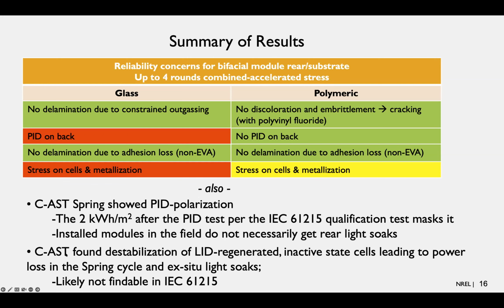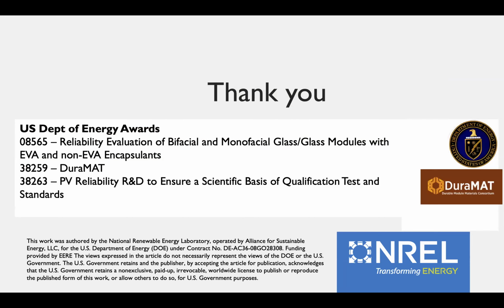Then we found that combined accelerated stress testing destabilized LID regenerated inactive state cells, leading to power loss in the spring cycle and ex situ light soaks. This is also not likely findable in IEC 61215, because that doesn't mandate going to a high temperature or anything more than 2 kilowatt hours per meter squared of light. So these two items we found, PID polarization and destabilization of LID, could happen in the real world and wouldn't be found in the standards. So that's the end of my talk, and I'd like to thank the support of these projects here.